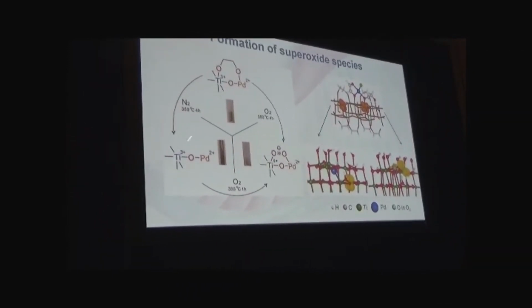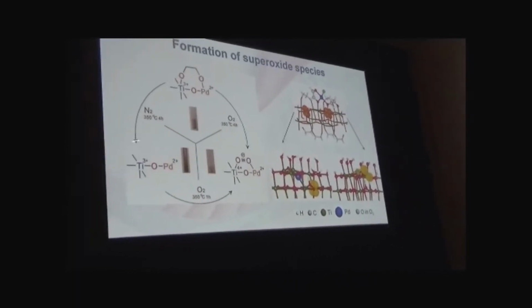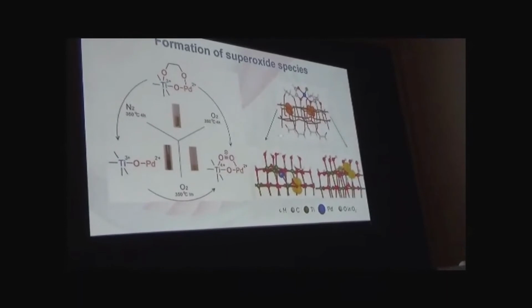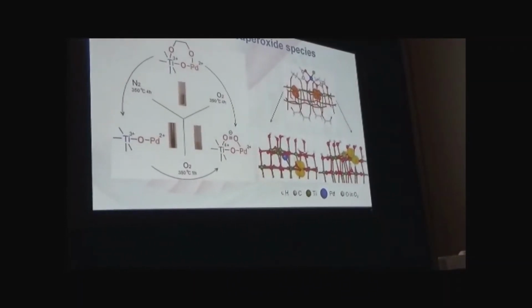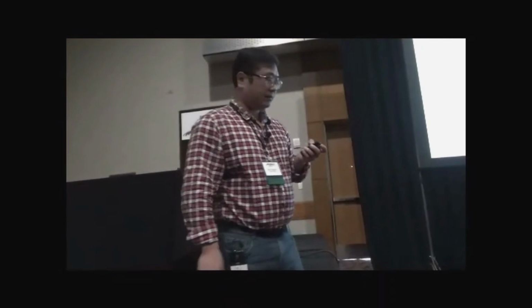This one, and then we can add in the nitrogen. In this one, our calculation also confirms the spin indicator, which one has been reduced. In this case, it's the titanium. And in this case, the oxygen, the electron will transfer to the oxygen to make the superoxide species. And superoxide species will help to oxidize the CO.